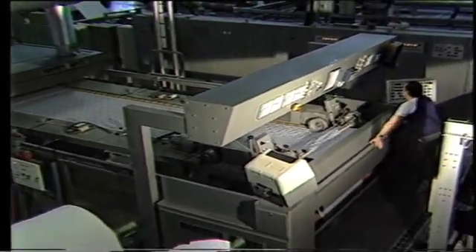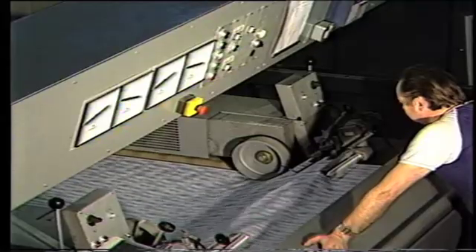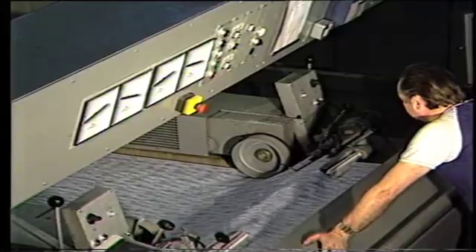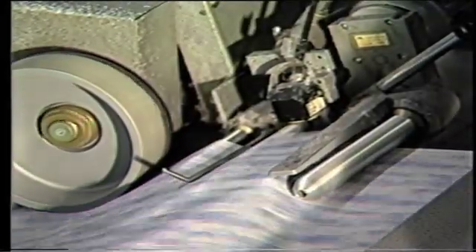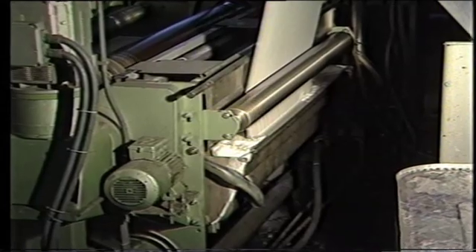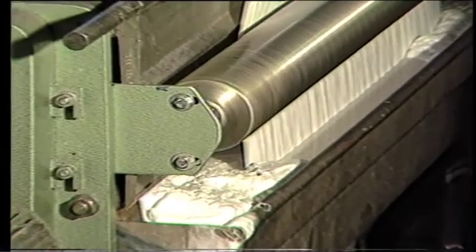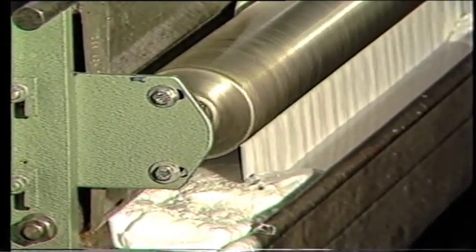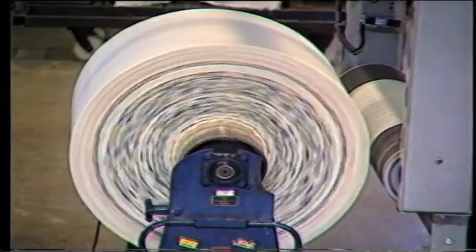A new stenter, costing £350,000, ensures that once again the fabric is width corrected and weft straightened after the distorting effects of the previous treatments. In addition, resins and softeners are applied by the stenter to the fabric. In general, softeners are applied to dresswear and resins to furnishings. They diminish the shrinkage and improve the washing and handling properties of the fabric.